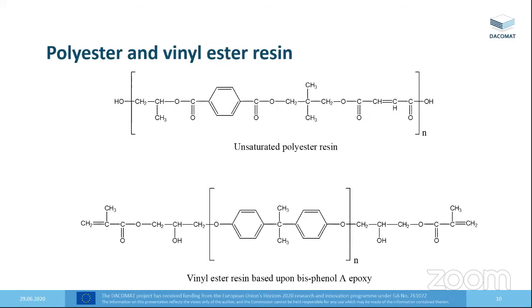So one of the things we were interested in was looking at the impact of an unsaturated polyester resin versus a vinyl ester versus an epoxy, which I haven't shown here. The vinyl ester is the resin of interest from the point of view of external applications, because a vinyl ester, if we look at the structure of these resins, is much more tolerant to moisture than an unsaturated polyester.